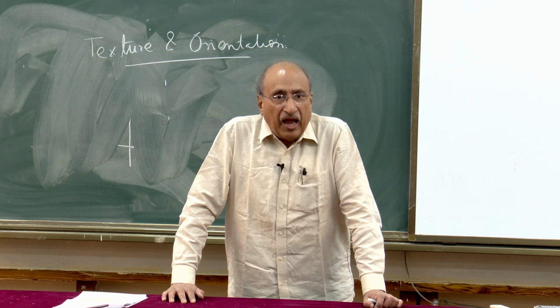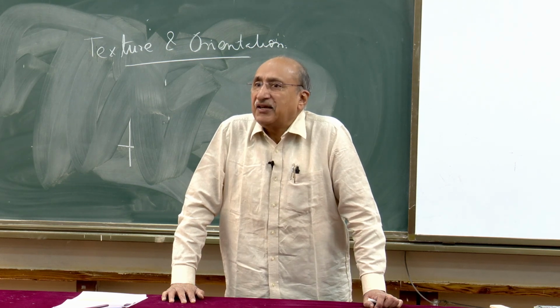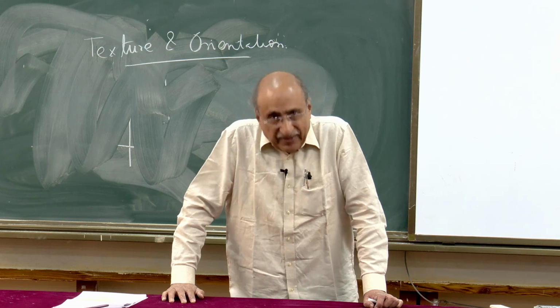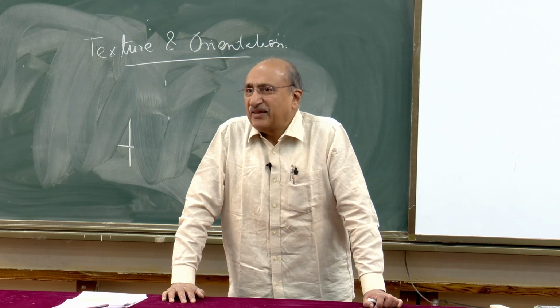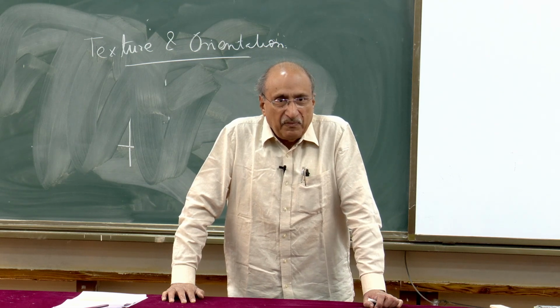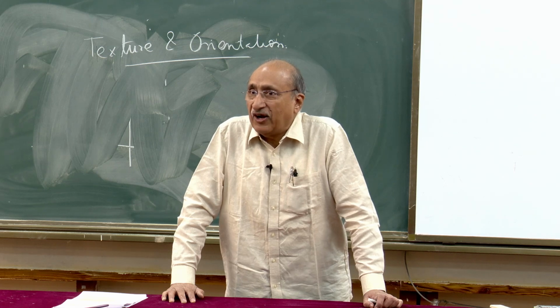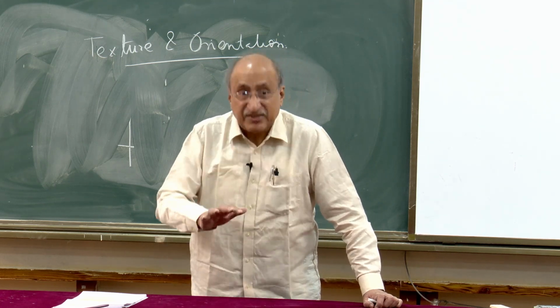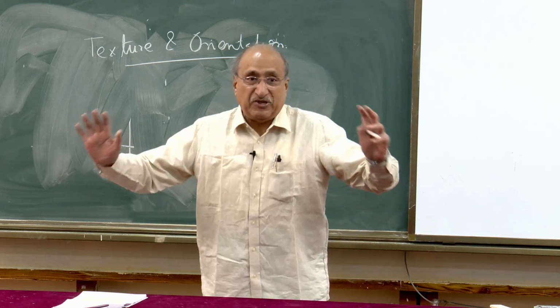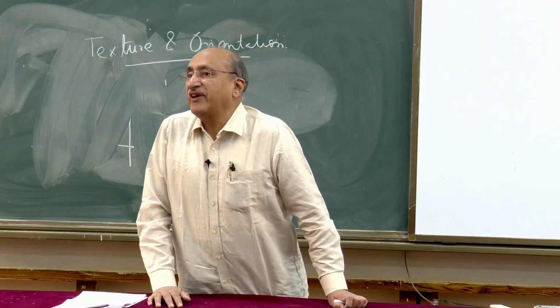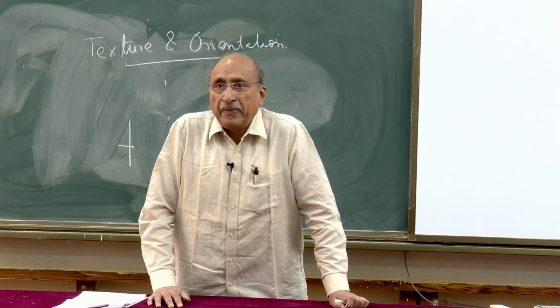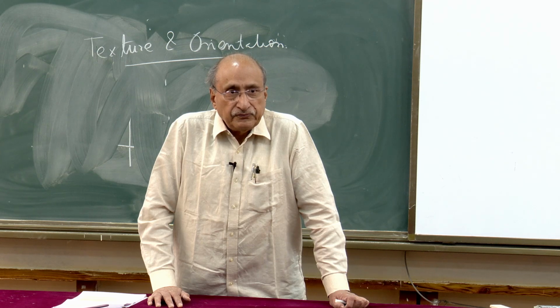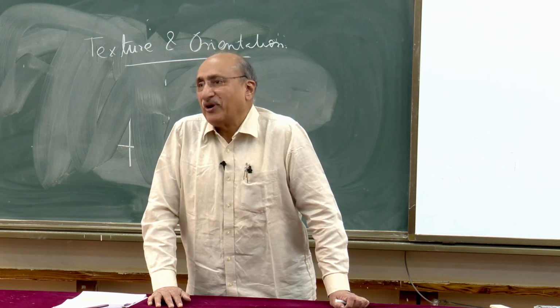If you have the good fortune of working only on single crystals, of course you will have difficulty making them, but if you make them, then life is comparatively easy. But for polycrystalline materials, life is more difficult because of this texture, which is an extrinsic factor. For the same material with the same composition, you could have completely different hysteresis loops, depending upon how you have textured and oriented them. Then your life is a little more difficult.